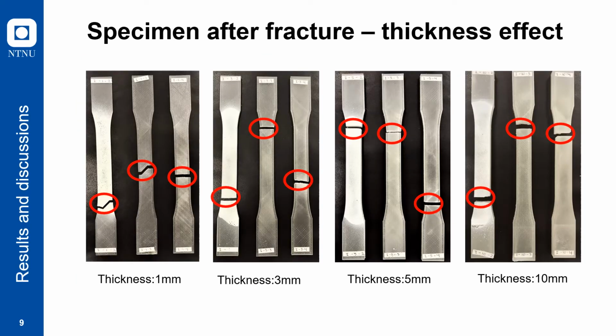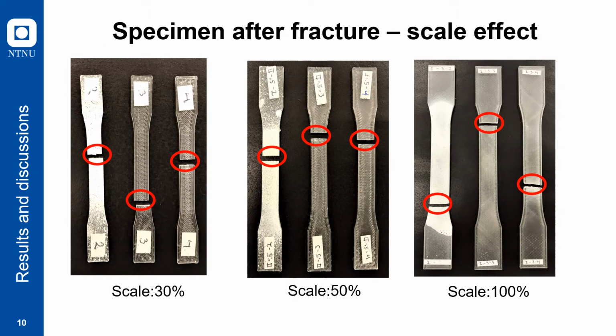So these are the specimens after fracture. This is for the thickness effect. I chose 3 out of 5 to be listed in here. As you can see, all the fracture surfaces are within the gauge area. Some are more close to the middle, and some are within the edge of the gauge area. And similarly, these are for the scale effect. All the fracture surfaces are in the gauge area. Some are more towards the middle, and some are in the edge. The detailed reason I will explain later.